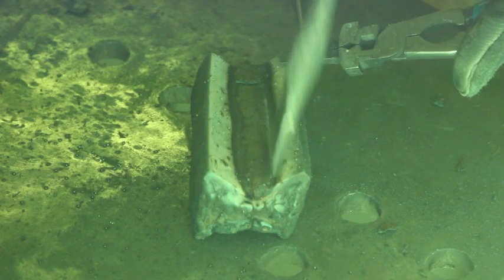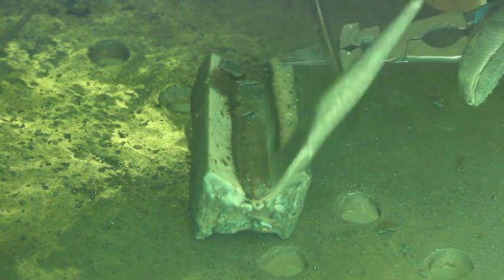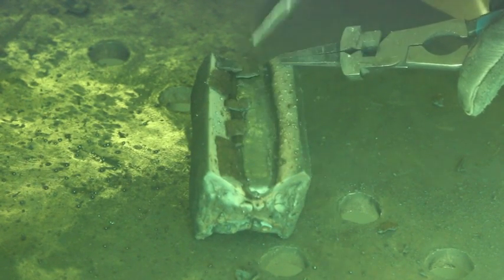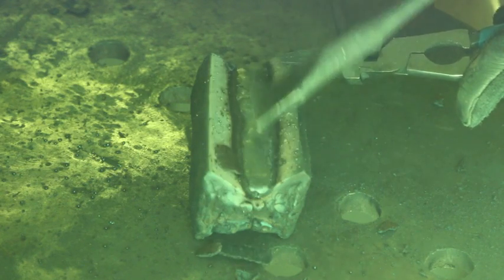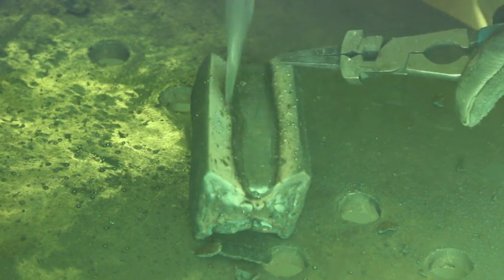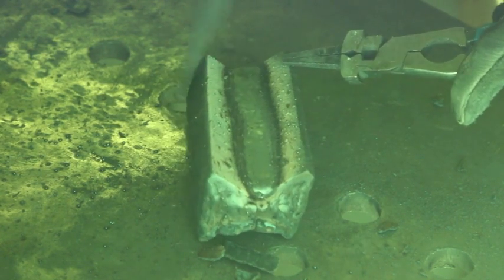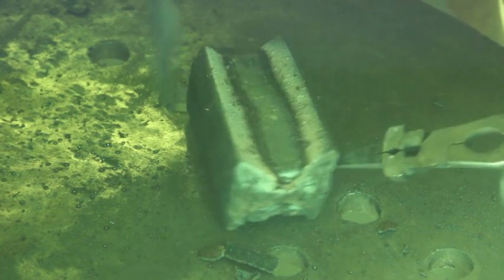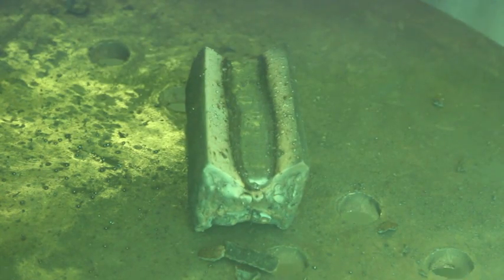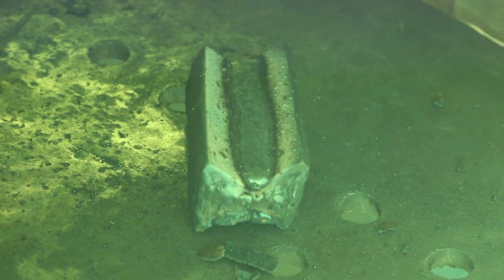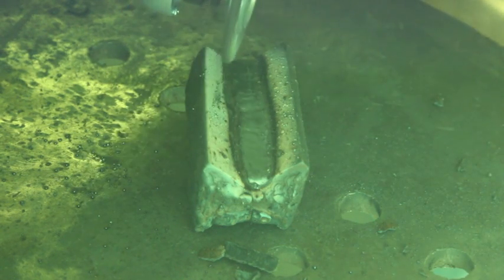And the reason for that is you're trying to stay ahead of the slag the whole time. This slag, if you take a look at it, I'm chipping it off and it's coming off really nice, but look how thick that stuff is. It's extremely thick, and if you don't stay ahead of it, if you don't keep it at bay, this stuff will overtake you and you will have slag inclusions. Slag inclusions are very, very easy to come by in this process, so you really have to watch out.